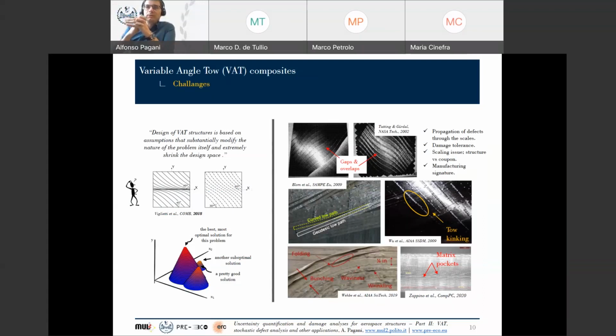All these defects, of course, finally will affect the mechanical behavior of the final component. And at the moment, most of the design tools for the fabrication and design of this kind of variable angle tow composites do not take into account these defects. So when you go into an optimization process, inevitably you will find maybe just a few local minima. So you will never be able to optimize your structure in the best, most optimal solution. But you will usually find a local minimum because you are not taking into account these defects. These defects indeed are a function of the manufacturing signature, which means the machine design parameters and fabrication procedures.